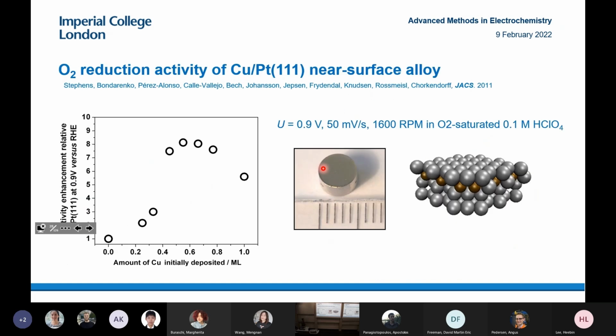So we also went ahead and measured the oxygen reduction activity, and we found that we could see up to 8 times improvements relative to platinum 111. So it's a really, really active surface, but if we put too much copper, we see lower activity.